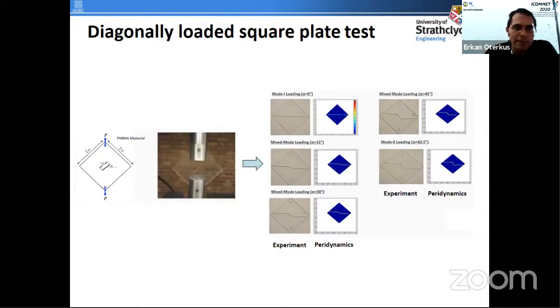As you see, there is a simple example here where we have some type of glass-type material, which is PMMA. In this particular situation, we have this diagonally shaped specimen, and there's an initial crack there, and then we apply tensile load from top and bottom. And depending on the crack orientation, the fracture looks different, as you can see here. The gray ones are experimental data, and the other results are from peridynamic simulations. If you look carefully, you will see that peridynamic simulations actually captured the correct fracture pattern regardless of the orientation of this initial crack.